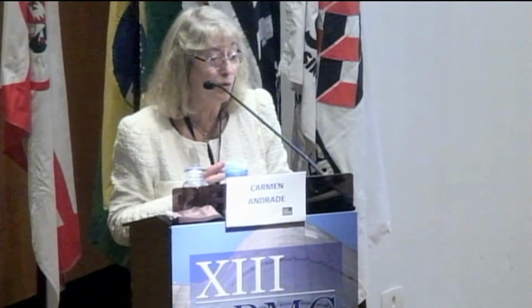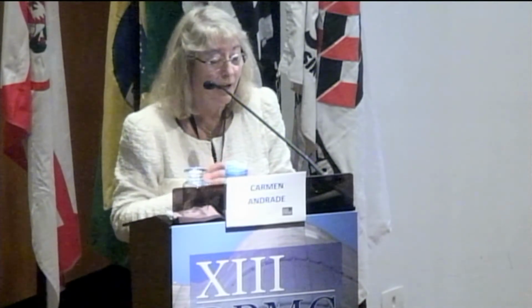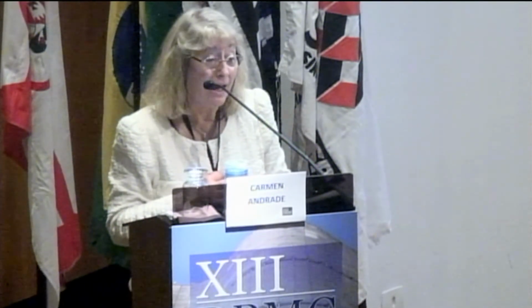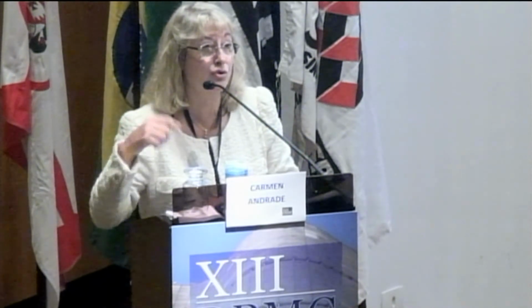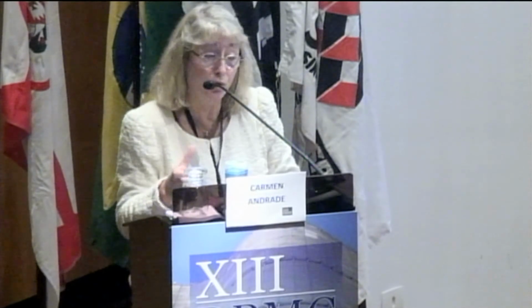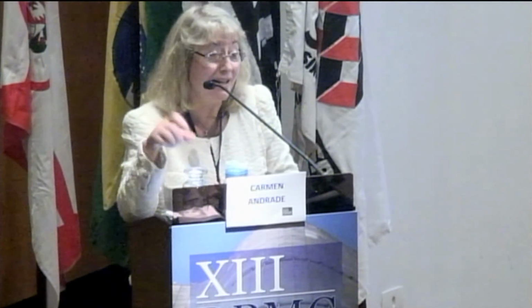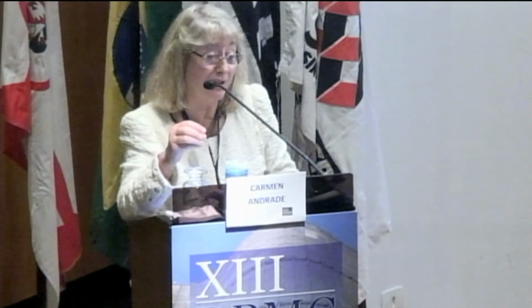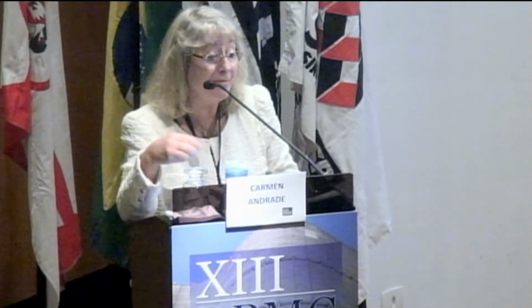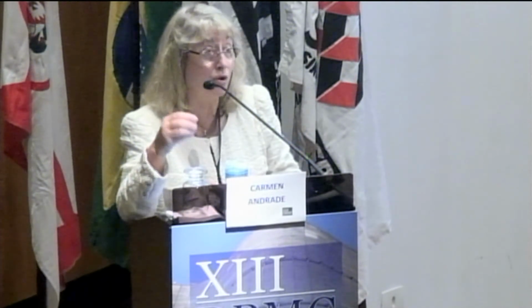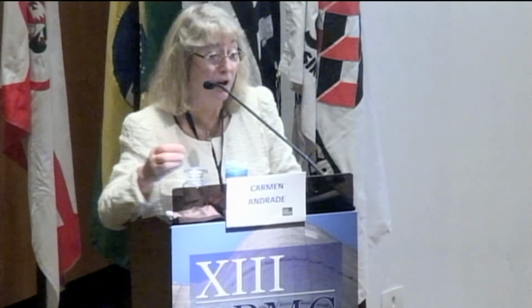Rio has 80% relative humidity all the year, at least the weather that was supplied to me, and the temperature is high. I was thinking that with typical values of 80% we shouldn't have carbonation. But it's 60 years old and was carbonated very much. The explanation we found with Ennio is that it is a porous concrete. In that case, the water mainly fills capillary pores, which allows enough empty space. So 80% is not saturating the pores, and if it is not saturating the pores, the CO2 can penetrate.